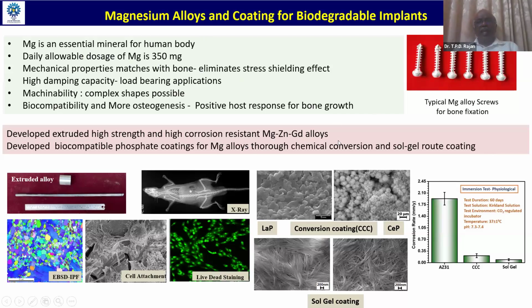And magnesium zinc gadolinium is one of the rare earths which is very widely used, and we also do the coatings, lanthanum phosphates, cerium phosphates, cerium and lanthanum, which are all rare metals, to control this degradation. So we have to have a degradation, but it must not degrade very quickly. So this is one of the very promising materials for bio implants, the biodegradable magnesium alloys, as well as the lanthanum or cerium based phosphate coatings, which are used to control the degradation.